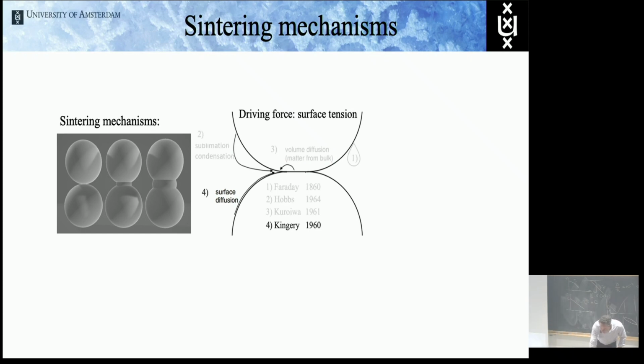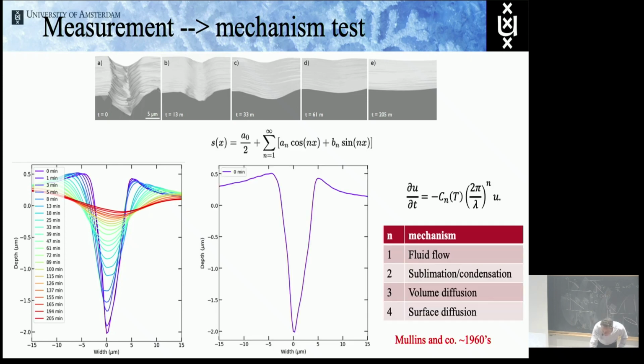And so the nice thing of this experiment is that we can make that quantitative. And Mullins in the 1960s actually wrote down a single differential equation. This is for a single sinusoidal perturbation of your surface. And he says that the amplitude change in time is some temperature-dependent prefactor times 2 pi over the wavelength of the amplitude to a power n times the displacement itself. So this single equation actually describes all the 4 processes that I mentioned to you, because if n is 1, we get fluid flow. If n is 2, we get sublimation condensation. If n equals 3, we get volume diffusion, and if n equals 4, we get surface diffusion.